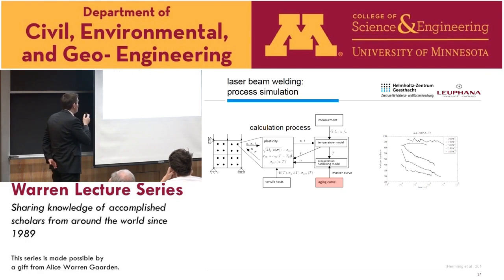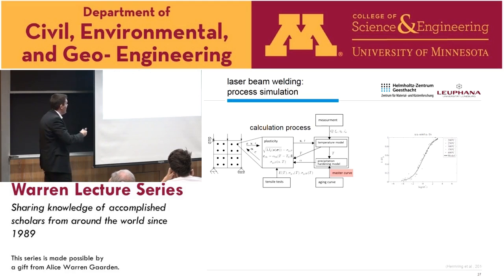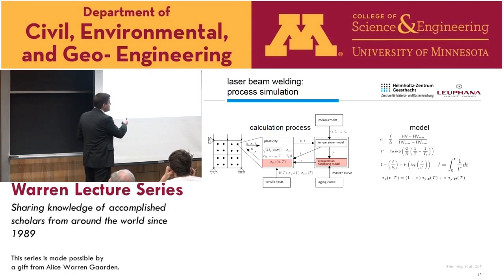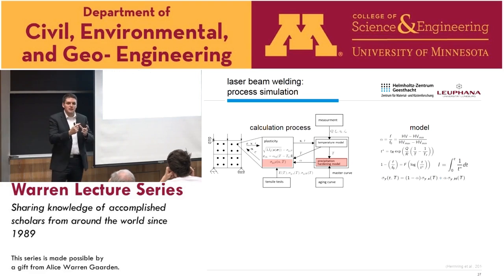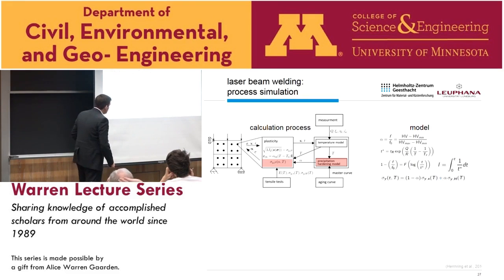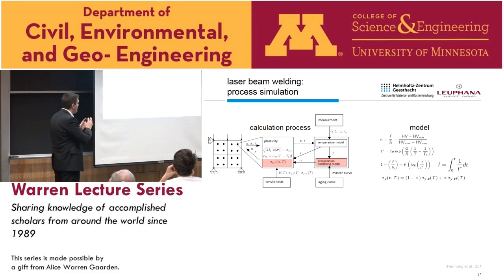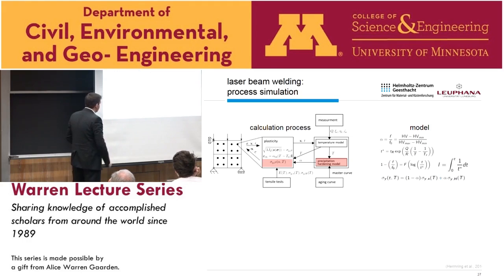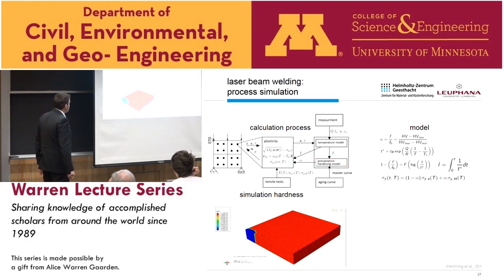For that, we investigated, for example, some aging curves. This is for 6005 out of the literature. Based on Vickers data, we did that also now for 2139. And by that you can get a so-called master curve, which in principle gives you a relation with respect to the volume fraction of your precipitates inside of your material in terms of temperature and time. We used a model out of the literature, very similar to the Robson model. This is coming from Myhr, from Norway, and this can then be incorporated in a kind of mixture rule, which accounts for material which is in the complete solute state and in the complete